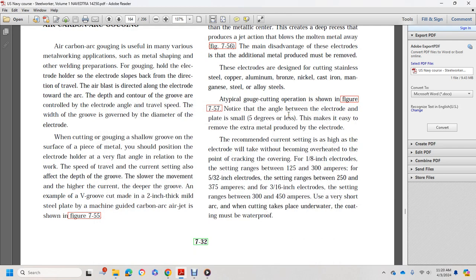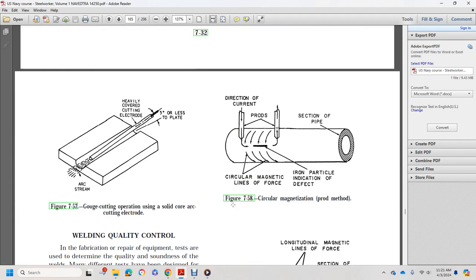The recommended current setting depends on the size of the electrode. For a 1/8 inch electrode, the setting ranges between 125 and 300 amps. For a 5/32 inch electrode, the range is 250 to 375 amps. For a 3/16 inch electrode, the setting ranges between 300 and 450 amps. Use a very short arc when cutting takes place underwater. The coating must be waterproof. Figure 757 shows a gouging and cutting operation with a solid arc cutting electrode.